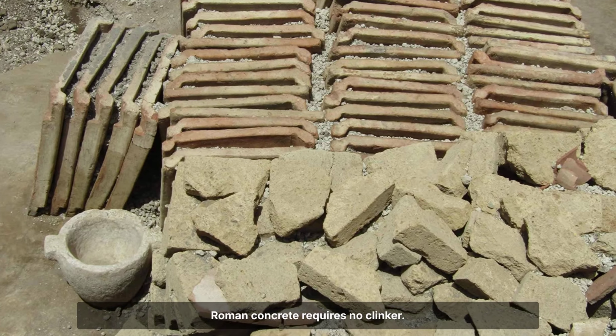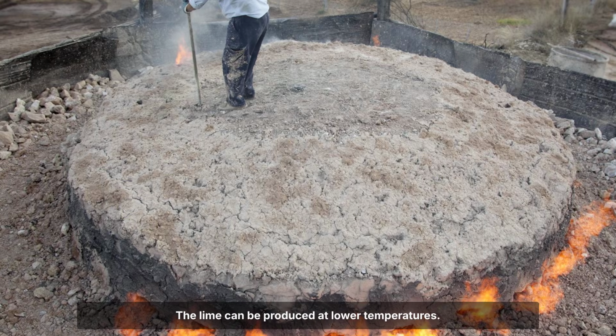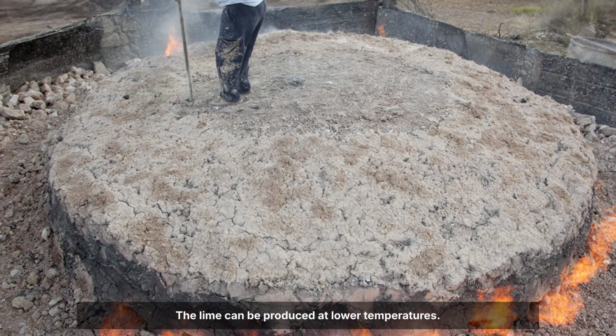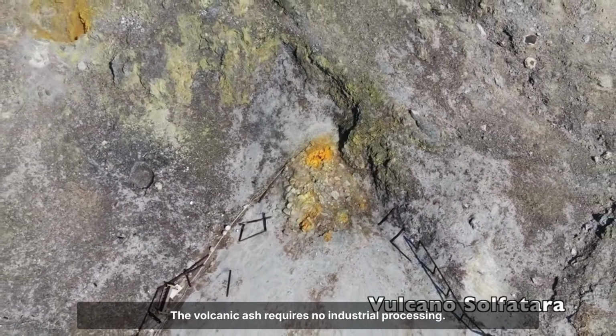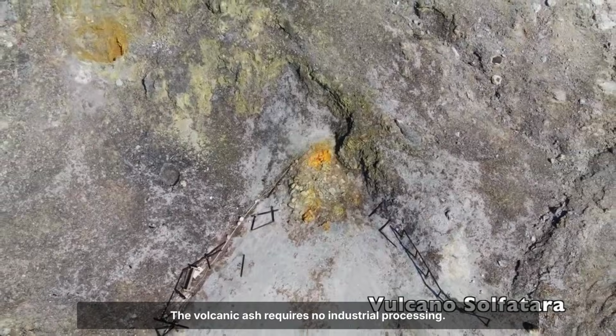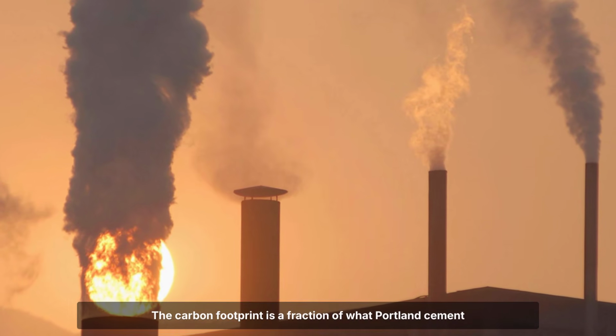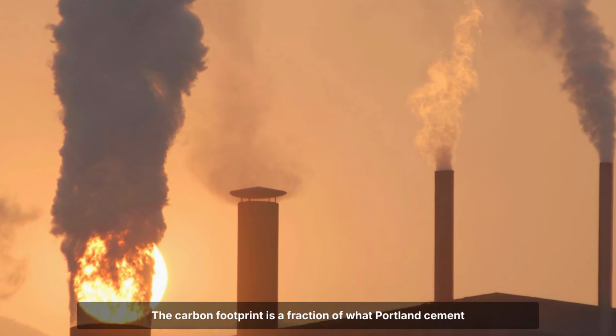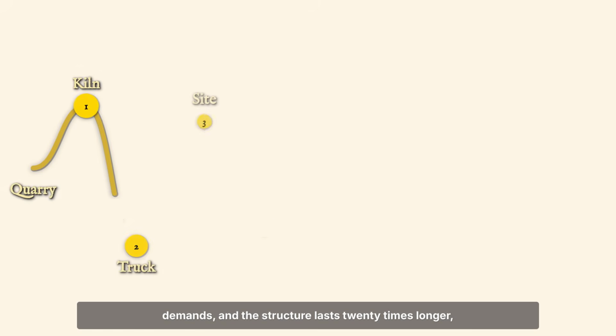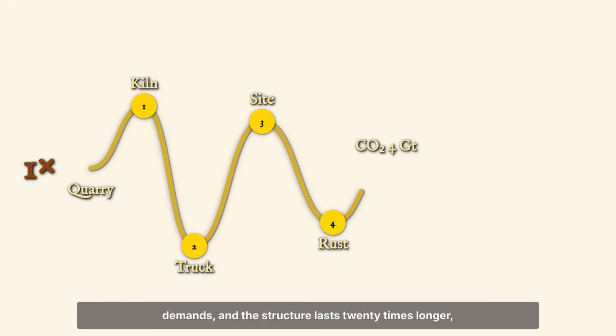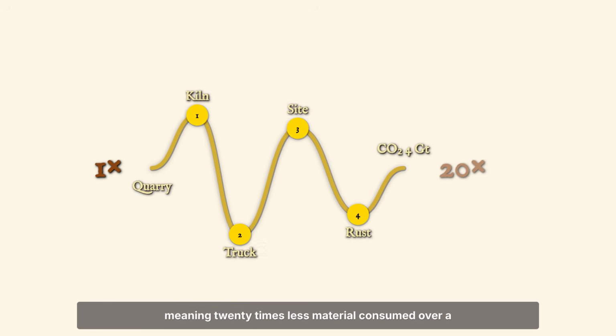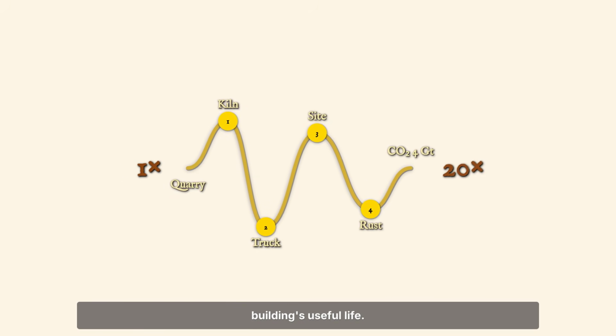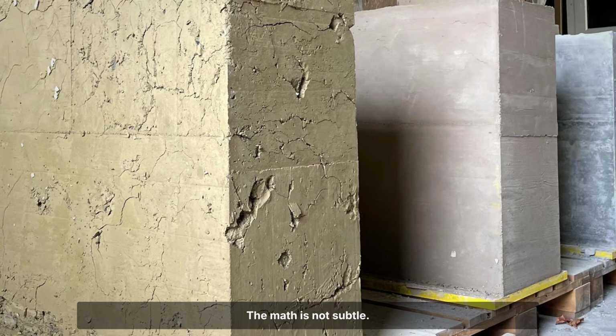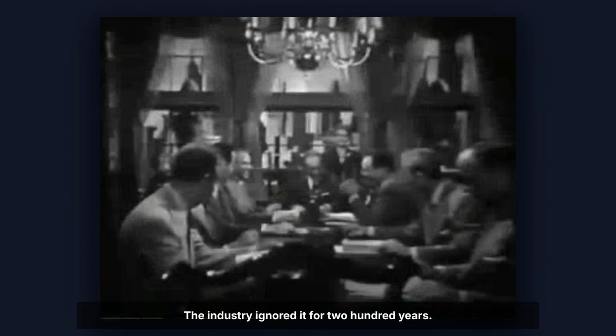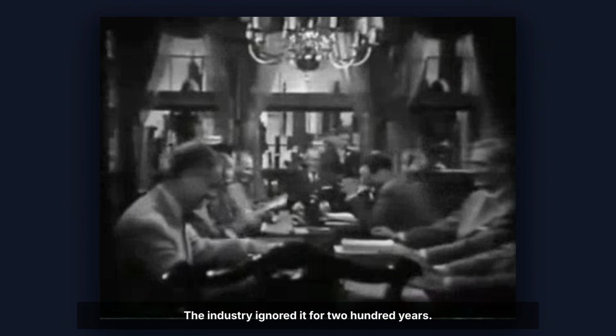Roman concrete requires no clinker. The lime can be produced at lower temperatures. The volcanic ash requires no industrial processing. The carbon footprint is a fraction of what Portland cement demands, and the structure lasts 20 times longer, meaning 20 times less material consumed over a building's useful life. The math is not subtle. The industry ignored it for 200 years.